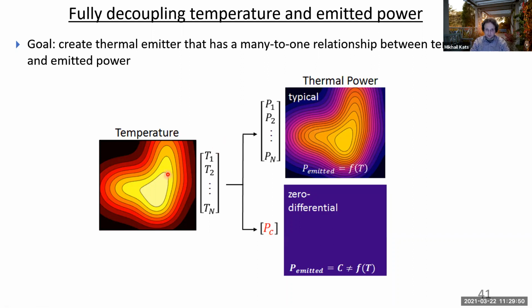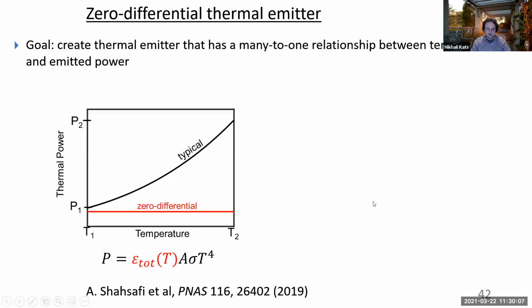So before, I was showing you that a spatial gradient of temperature maps to a spatial gradient of thermally emitted power. That's how infrared cameras typically work. And I wanted to break that. I wanted to make many temperatures map onto just a single thermally emitted power, so that you wouldn't get any information from an infrared image of this type. Fundamentally, what we're looking for is a plot of thermal power versus temperature, which is like a horizontal line. That's why we call this a zero-differential emitter, because we want this to have no derivative.